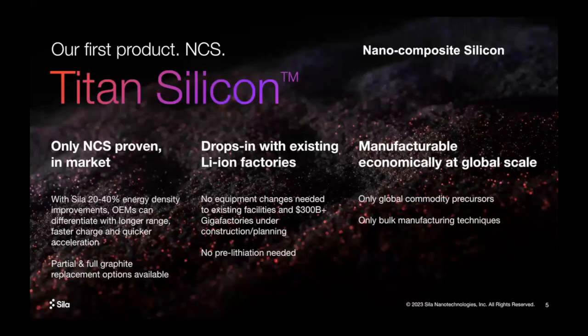So what we're making is what we're calling Titan Silicon. It's a nanocomposite silicon material. We are the only nanocomposite silicon material that's in market today. And you achieve about a 20 to 40% increase in energy density, 20% today, 40% in the future, which enables our OEMs to really differentiate from others because they're getting the longer runtime, the faster charge, and also quicker acceleration